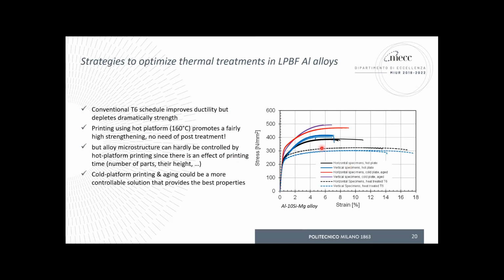For the same samples, here we have a collection of the tensile behavior, just to add some more information about the mechanical performance, depending on the thermal treatment we can promote on the alloy. So the dashed lines, apart from the vertical and horizontal orientation of the specimen, correspond to the standard T6: solution annealing, quenching, and then aging.